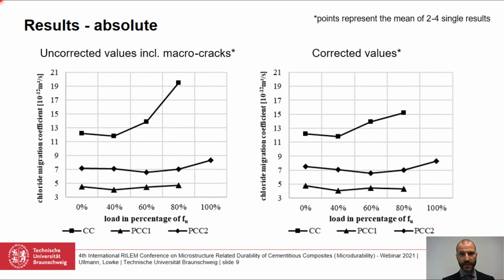The ones we depicted here are absolute results, so referring to the non-steady state chloride migration coefficient directly. It is depicted on the y-axis, and on the x-axis we have the load that we applied as a percentage of the ultimate load. So 0, 40, 60 and 80%, as well as 100 in one case. All these points represent the mean of 2 to 4 single results, and we depicted the uncorrected values as I showed you before, including the macro cracks on the left, and the corrected values that refer to the mean depth of ingress only on the right side.